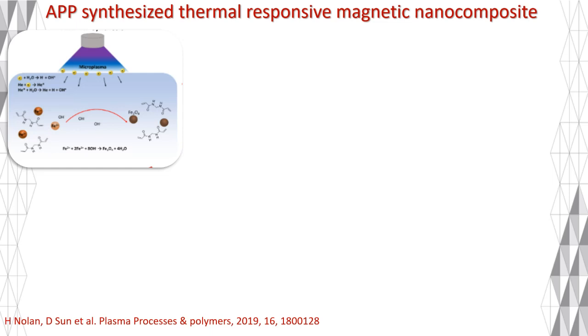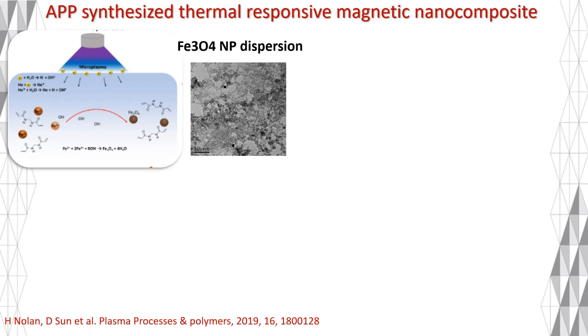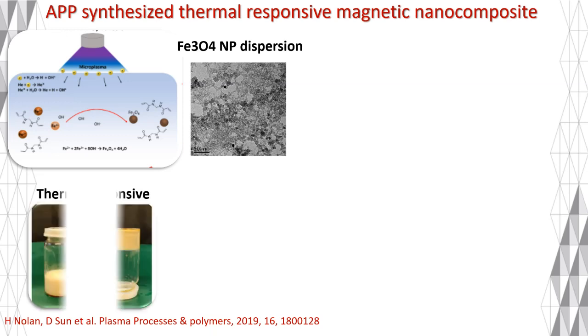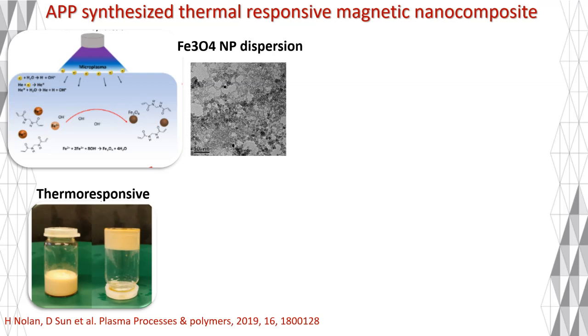Using a similar protocol, we have also successfully synthesized a magnetic thermoresponsive hydrogel composite. In this case, iron oxide magnetic nanoparticles were synthesized in situ within a thermoresponsive hydrogel. The resulting magnetic hydrogel composites exhibit a remarkable reversible phase change property at about 37 degrees. And this unique characteristic opens up the possibility of potential applications such as minimally invasive cancer magnetic hyperthermia.